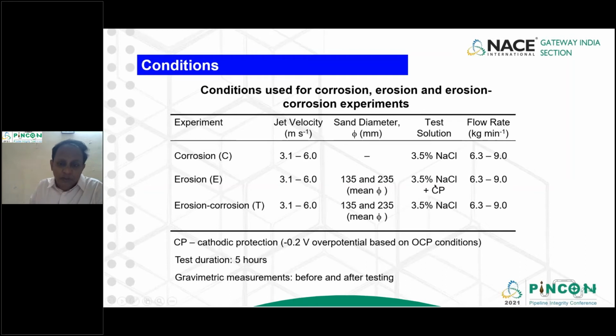Even though I am having a sodium chloride solution, I am suppressing or completely eliminating its corrosive nature by holding that substrate at a minus 200 millivolt overpotential. I'm calling it cathodic protection. You could ask me, I could go up to minus 1 volt. But if you go to minus 1 volt, other complications arise, like hydrogen gas evolution and all that. So in order to prevent that, I just go below the OCP of copper by adding a minus 200 millivolt. In that way, I'm achieving the erosion condition.